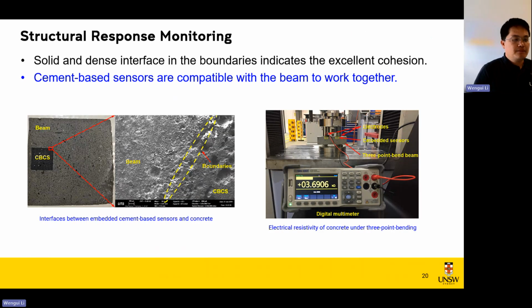Before the test, let's look at the microstructure of the interface between the cement-based sensors and the mortar beam. So basically, we found the boundary is very solid and dense. And this implies the cement-based sensors are compatible with the mortar beam, and they can work together very well. And here you can see the three-point bending test conducted in the laboratory.